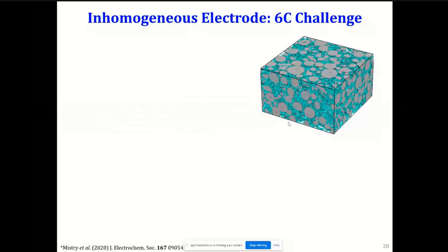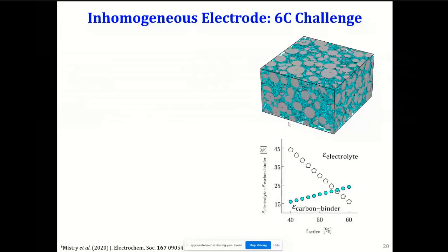Now, if I take an electrode, a large enough electrode sample, and we had to get this from tomography, what you get is something like this. The average active material volume fraction for this electrode was about 50%, but there was a large distribution. The lowest active material volume fraction was about 30, the highest was about 65. Correspondingly, the local distribution of carbon and binder would also be different. And now the third phase sort of sets itself. So it would then lead to an opposite distribution of electrolyte, right?